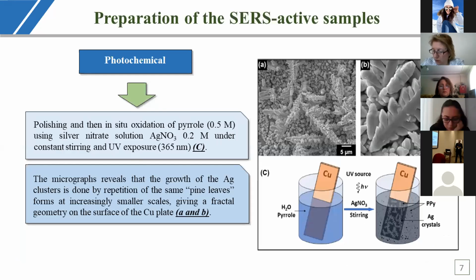In the second method, a photochemical approach was realized based on an in-situ oxidation of polypyrrole using silver nitrate and UV irradiation on a copper plate. An electronic transfer occurred between the monomer and silver cation, leading to the formation of polypyrrole and metallic silver at the same time. The topography of the electrode surface revealed the growth of silver by repetition of the same pine-leaf form, giving a fractal geometry, as we can see here.